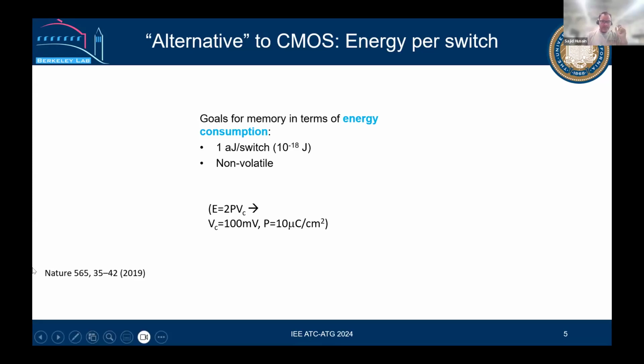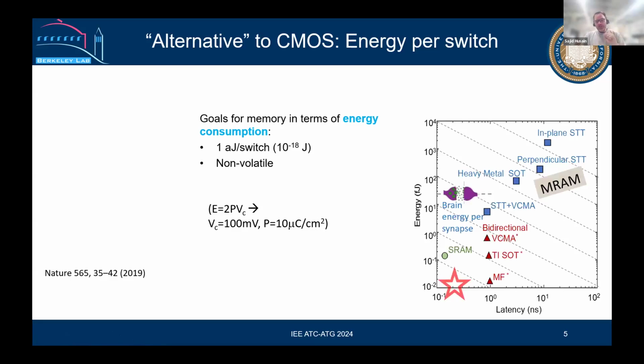So my proposal here is that if we use some material and calculate the energy, it's basically 2 P into VC, which is a random number here. I should not introduce it this way, but P is the polarization of the material, the electrical polarization, and VC is a switching field, a switching voltage. If you multiply these two, you end up with a number in the attojoule range. If you compare with the existing technology on spin-based and some other technologies, this star number goes very low, into the attojoule range.